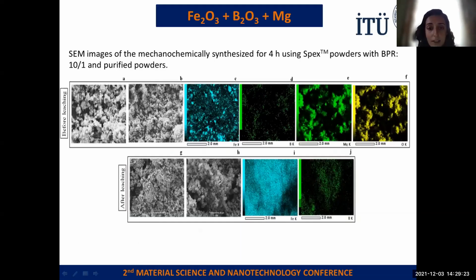And these are the SEM images of the synthesized nanoparticles belonging to the first batch. They look like nano sized, irregular shaped, also like spherical shaped nanoparticles after the leaching. We have this type of particles. Also, elemental mapping results show us that the magnesium and oxygen are located in the same areas, and it shows us the magnesium oxide formations.